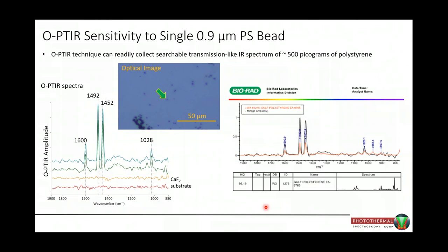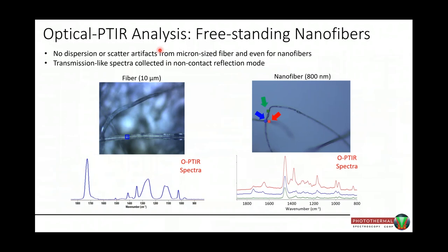We can look at fibers. This is a freestanding nanofiber, so you don't have to examine a whole fabric. You can actually go in and look at a single fiber. And this is an acrylic fiber that we got a spectrum of, and also down to a nanofiber, in this case an 800 nanometer fiber. We can collect very nice infrared spectra on two different fibers there.